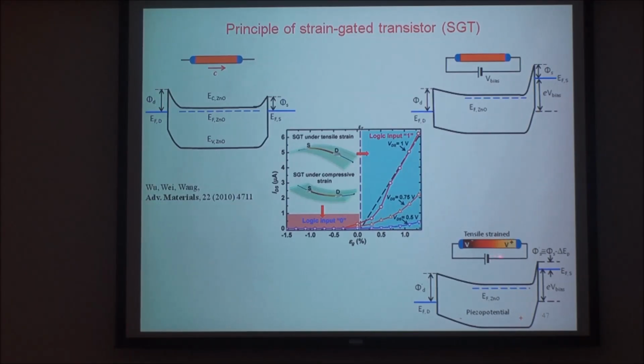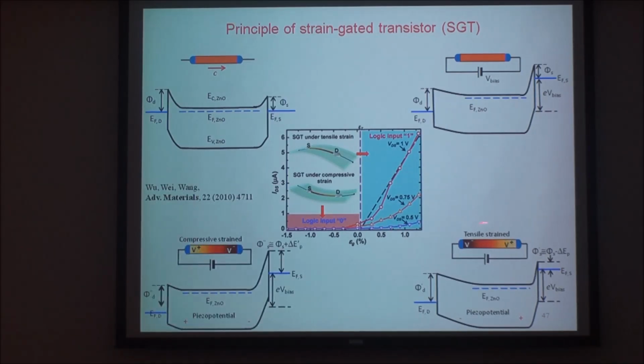Now, the electrons flow this way. If this is a positive piezo potential, it lowers the barrier height, so electrons flow more easily. This is the effect you see. The larger this potential, the easier it flows. Conversely, if you go from tensile strain to compressive strain, this is the lower piezo potential side. It raises the barrier height, prevents electron flow this way, and cuts it off. This is what you see here. This on-off ratio is about 500. So you can use this as a switch.